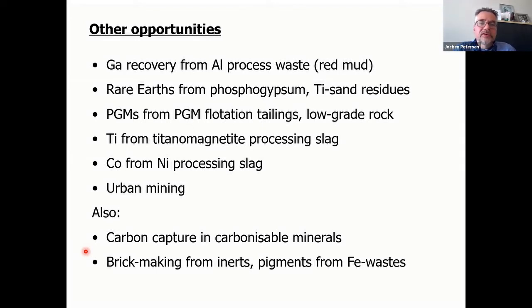Rare earths from phosphogypsum, as well as titanium sand residues. Those are two very different waste streams from two very different industries. Both of them, rare earth, there are hardly any deposits that have concentrations of rare earth on their own to just process them directly. In most cases, the majority of rare earth are associated with other minerals.